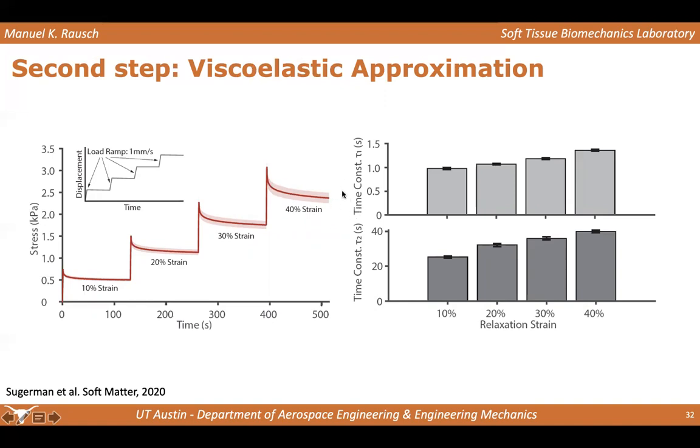And interestingly, we find that the first time constant falls in the range of a second, while the second time constant falls in the range of tens of seconds. And this is interesting because, although this is not proof, it kind of implies the existence of maybe two different physical phenomena that drive these viscoelastic effects.